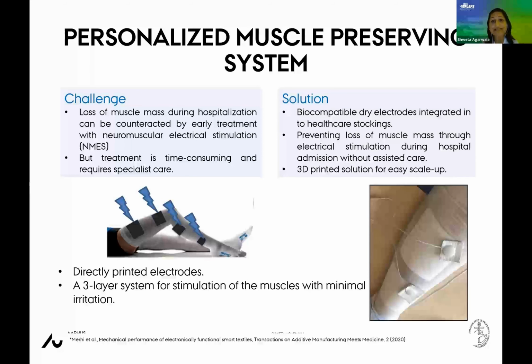So what we basically did was we made our own biocompatible electrodes. It's a 3-layer electrode system that we made, and we directly printed it into a compressive stocking, which is a textile commonly used in hospitals. It's mostly worn by ICU patients. And then we connected the wires to it and to a stimulator.